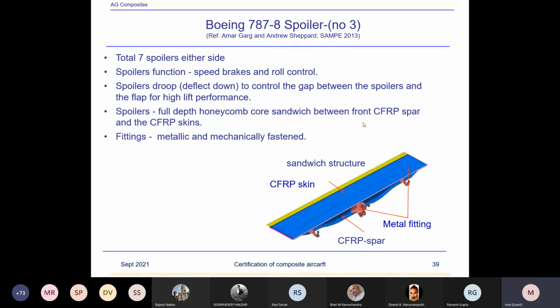So spoilers are full depth honeycomb core sandwiched between the front CFRP spar and the CFRP skin. So you have this carbon spar, carbon skins, and it is a honeycomb sandwich structure. Now, the process to manufacture this is autoclave. One would ask, why not RI? Of course, you can't use the resin infusion process for a sandwich structure. The reason being, if you try to use resin infusion for a sandwich structure, the core cells will get filled with the resin. And so that's why you have to use the autoclave process.